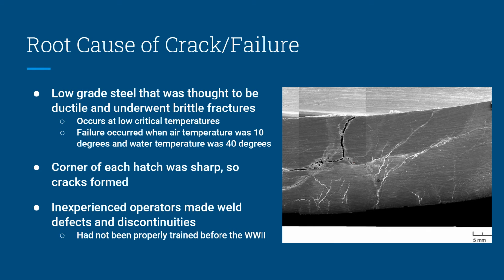So now let's dive into the root cause of the crack/failure. Knowing what we know now, this failure was most likely due to the low-grade steel that was thought to be ductile and underwent brittle fractures, which usually occurs at a low critical temperature. And this makes sense in our case because at the time the SS Schenectady failed, the air temperature was about 10 degrees and the water temperature was 40 degrees.